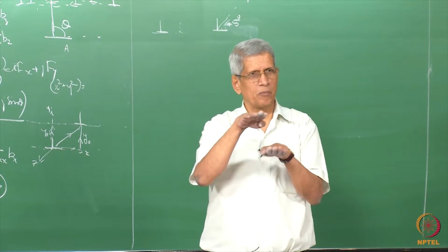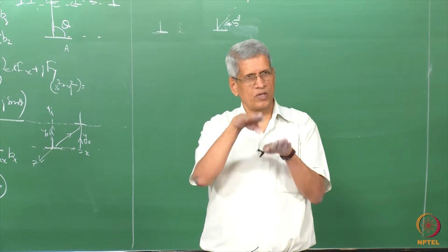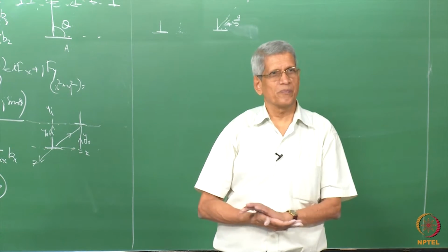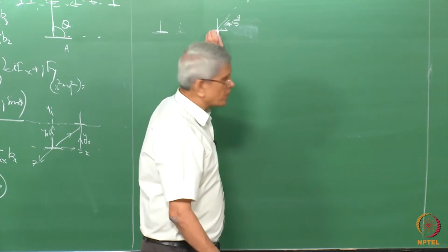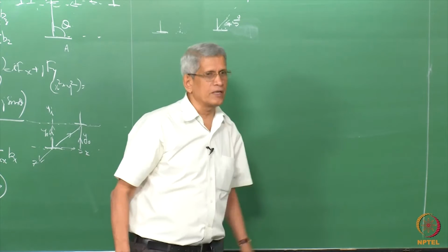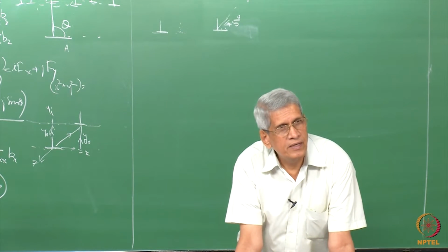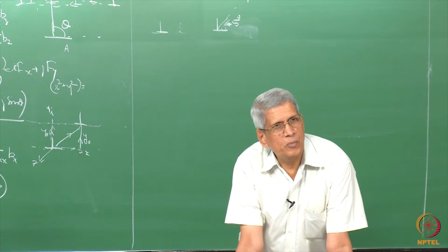Now they have become a coupled dislocation. The stress which will be required is to make this couple itself move. This sort of situation, when you have a positive edge dislocation and a negative edge dislocation on two different lines joined together like this, you know what it is called? This is called a dislocation dipole.